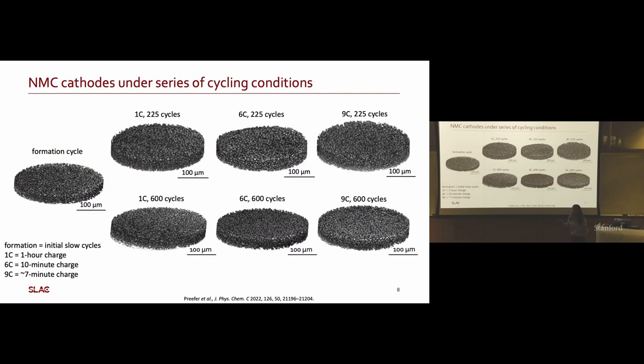Okay, so here is all of the 3D images that we have, and it's really hard to see anything when you're just looking at pictures, but it gives you an idea of what states we did. So we did the formation cycle, which is just a bunch of slow cycles. It's pretty standard. Every battery that comes out of a factory has been formed already. And then we did a series of faster cycling. So 1C is 1 hour charge, 6C is 10 minute charge. Then we actually went up to 9C, which isn't quite the right way to calculate it, but it was a 7 minute charge.